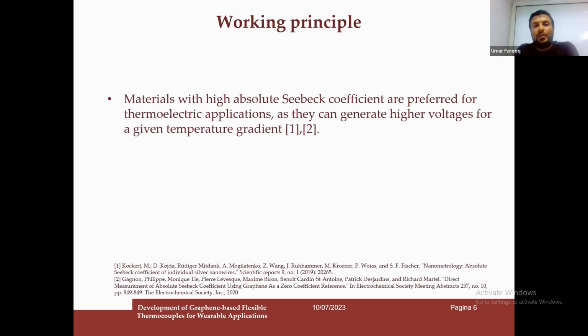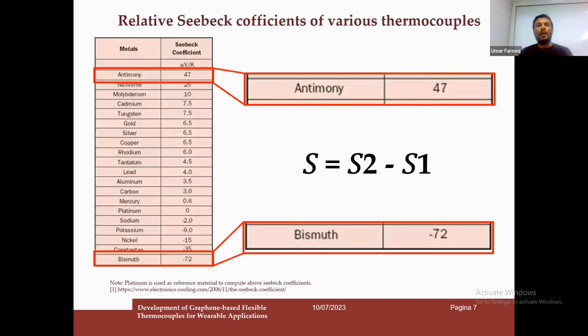So normally the materials with a high absolute Seebeck coefficient are preferred for making this type of thermocouple because they generate higher voltages with respect to the applied temperature gradient. So we can look at the relative Seebeck coefficient. Here is the table of different metals and their corresponding Seebeck coefficients. If we want to make a good thermocouple, then we have to take a combination that makes a large difference between their Seebeck coefficients. We can take the example of antimony and bismuth: if we combine both of them, then we can get approximately 119 microvolt per Kelvin difference. So this is a good combination for making this type of thermocouple.